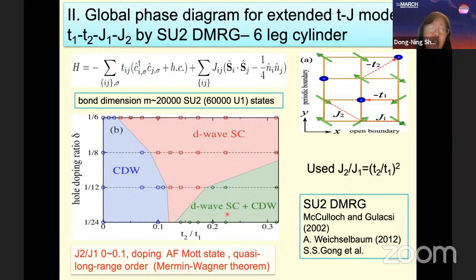If we go to even larger T2 over T1, and also focus on the lower doping region, we get a superconducting phase coexisting with CDW. So if we just increase the hole doping ratio, at lower doping we can be in this coexistent phase, then doping will induce a transition to the pure D-wave without stripe.